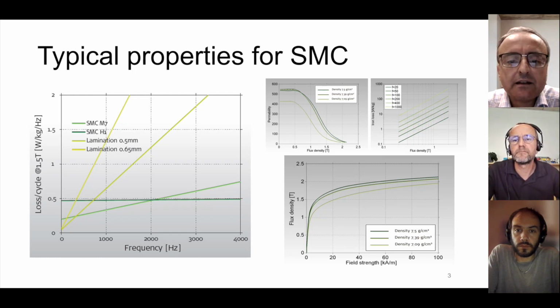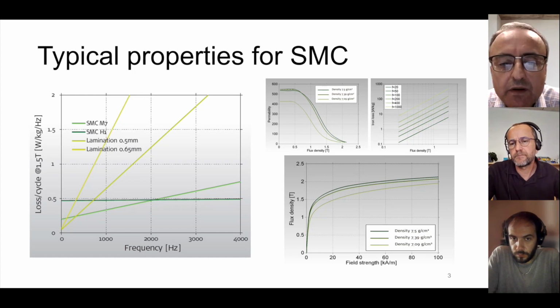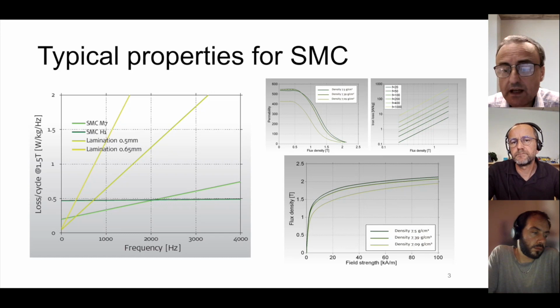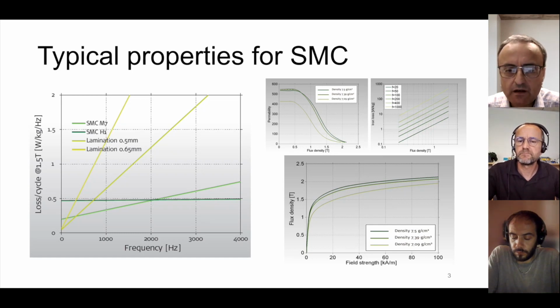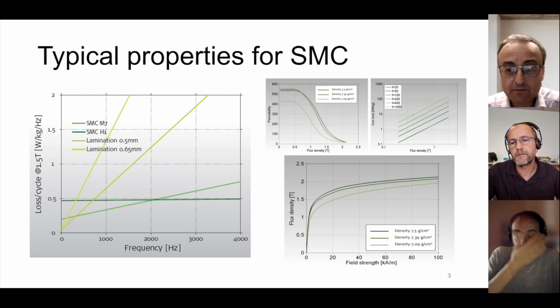It's very interesting. As you can see, the differential permeability actually goes down pretty quickly. When you go above, let's say, 1.5 and approach 2 Teslas of flux density, you can see the permeability going down very quickly, to the order of 100 or less, tending to maybe 10 or even less. Obviously this has to be kept into account very carefully when you design the machine. So these materials are very interesting from some points of view, but on the other hand, they do require a design process more tailored to their properties. You need to understand very well how the machine operates, and even envision how to best exploit the properties of these materials.